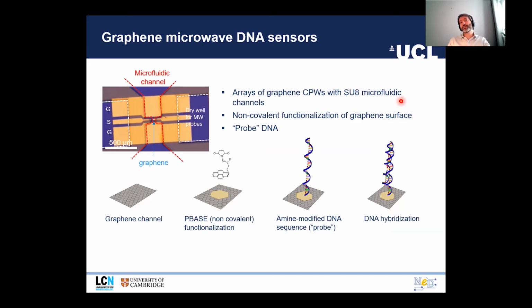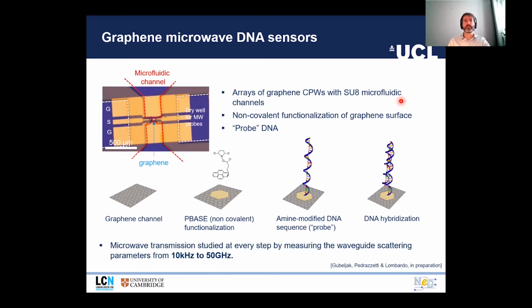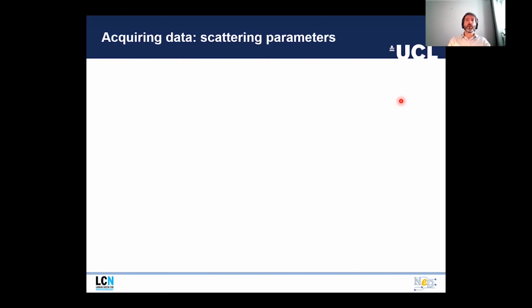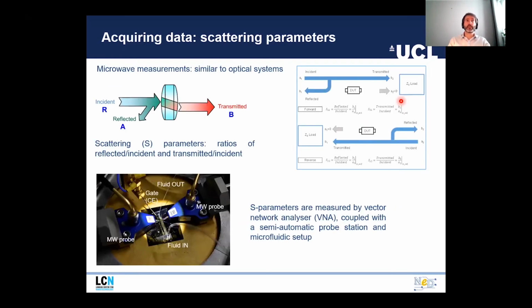And then once the complementary sequence is introduced, we have DNA hybridization, which results in a charge transfer and therefore a change in the graphene conductivity. So we do that, and we study the transmission from the kilohertz up to about 50 gigahertz. We acquire data using a vector network analyzer and scattering parameters. You can see the setup.